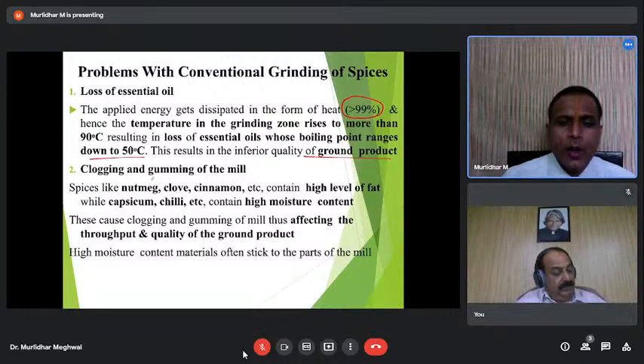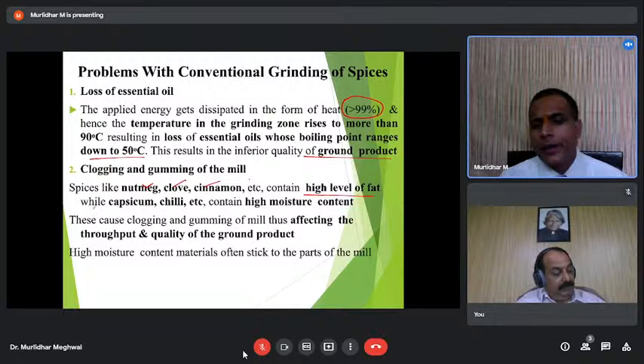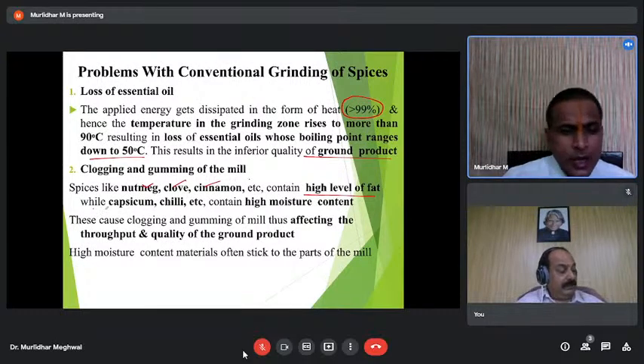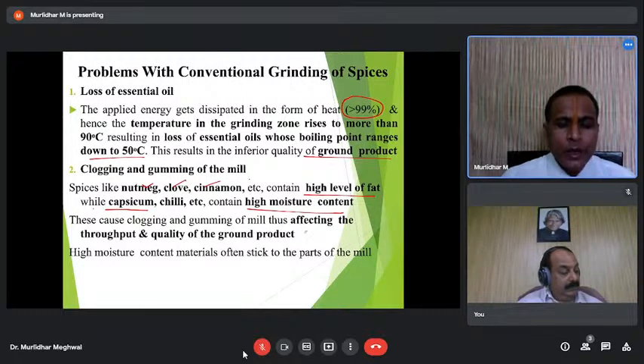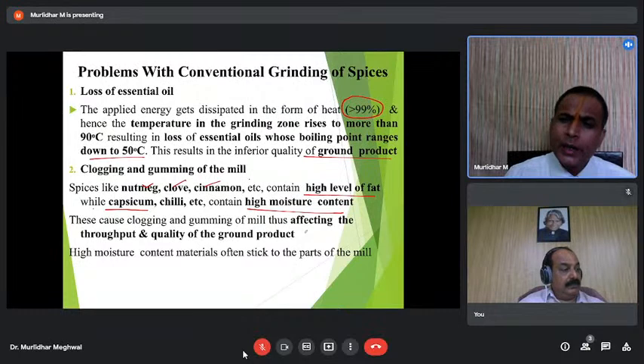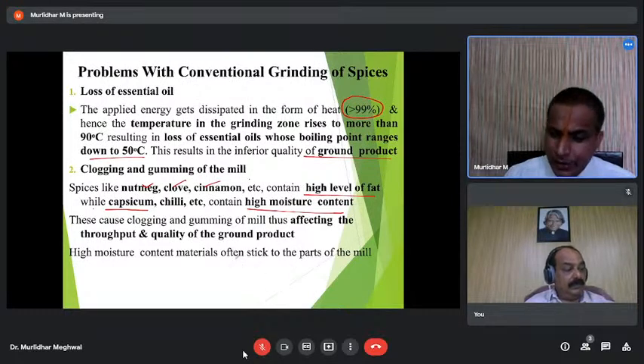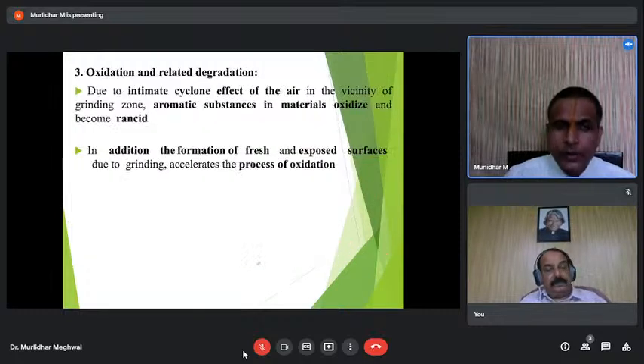Then there is clogging and gumming of the mills. Some of the spices discussed, like nutmeg, cloves, cinnamon, ajwain, contain high levels of fats, and when we grind them at high temperature, they release their oil, which clogs the mills. Some spices like capsicum and chili have high moisture content, so that can also lead to a clogging or gumming problem. Due to this clogging and gumming, one problem is in operation, and the other problem is that it affects the quality of our products. These high oil content or high moisture content materials will stick to the parts of the grinder when we use the conventional method.